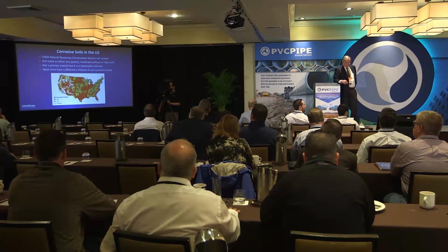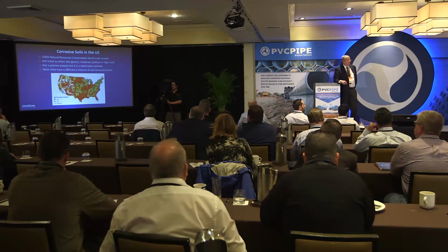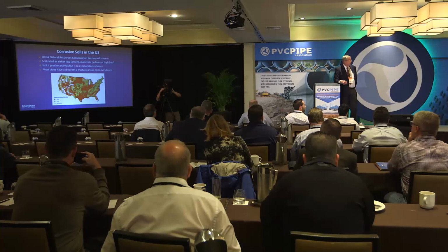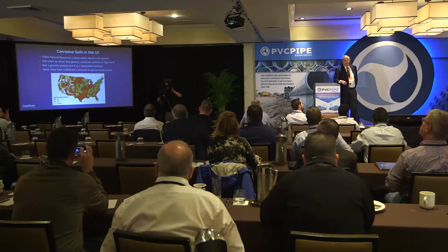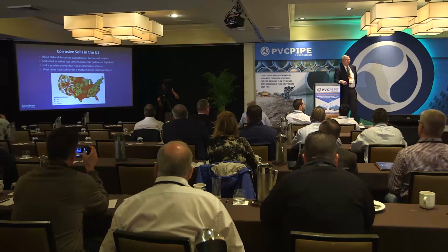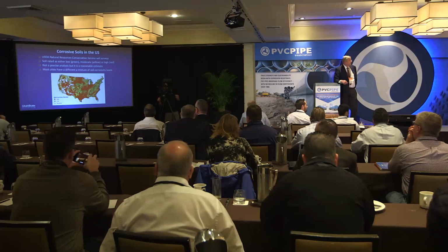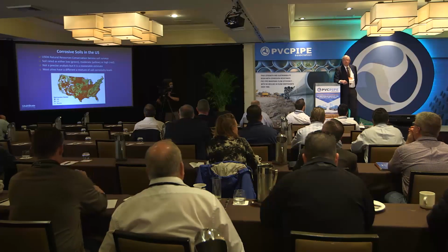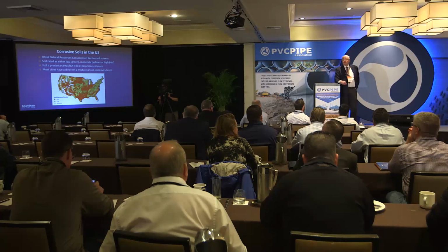The USDA has a website where they've gone in and quantified in certain regions what kind of soil you have into three categories. You can have green, yellow, or red for low, moderate, or high soil corrosivity. They don't have it for everywhere, but where they do, we could get some idea of the relative corrosive nature of the soil. It's not a precise measure. This is for unprotected steel in the soil, but it's the best numbers I've got.